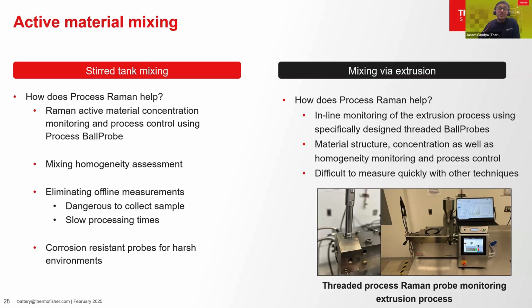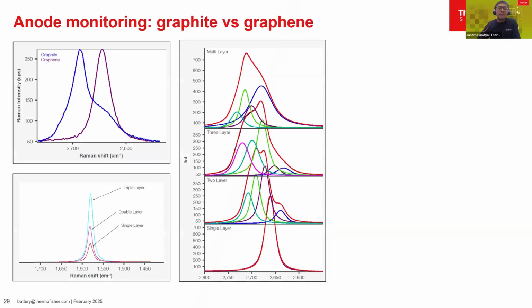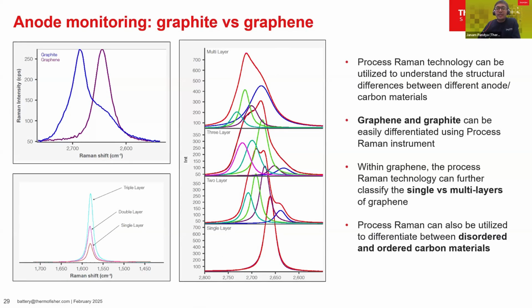But can Raman really characterize different materials? Let's look at that in the next slide. Process Raman can be utilized for both anode and cathode material characterization, as shown in the top left figure. Raman can differentiate between both graphene and graphite structure of carbon. Beyond that, the technology can even further classify single versus multi-layers, as well as ordered or disordered carbon materials. The combination of peak position, peak heights, peak shape, and peak ratio can be utilized to characterize such different properties of anode material.